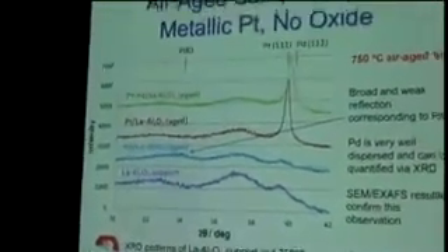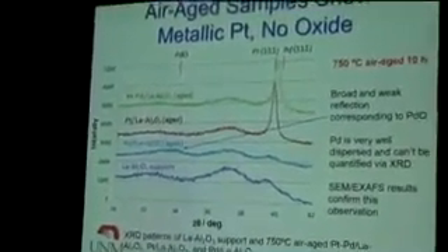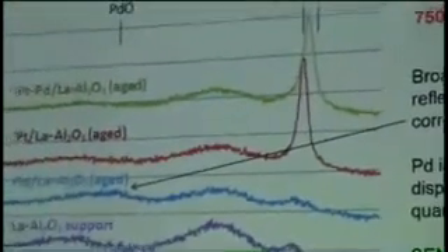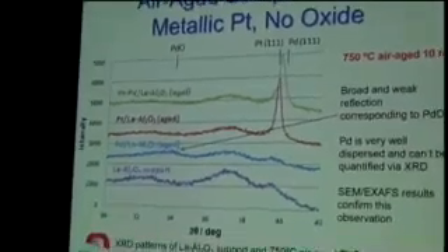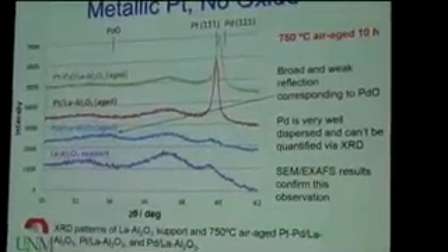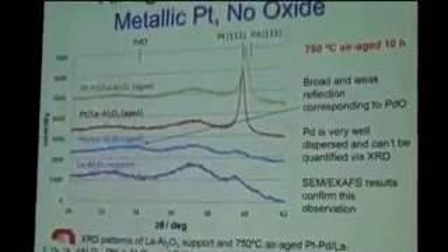These catalysts are all aged at 750 C for 10 hours. And there is the alumina support. Then you have palladium, you have platinum, and you have the bimetallic. The bimetallic, as I say, is roughly 1-to-1 in mole ratio. Actually, we have a little extra palladium than platinum. So the first thing that we notice is if you use the platinum catalyst, it forms this nice, large, sharp platinum peak.